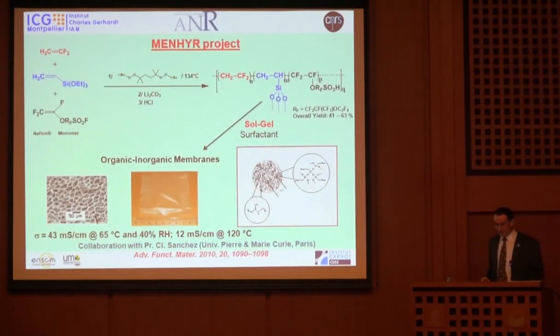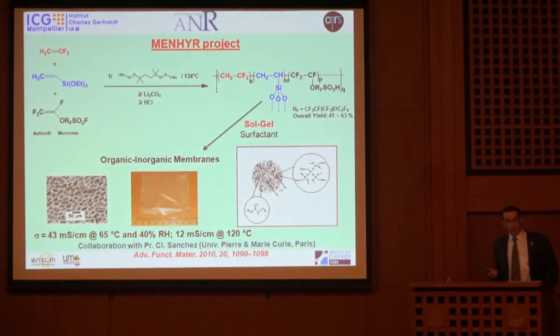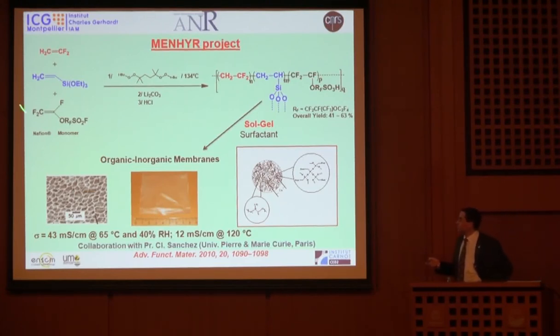So the approach we had in the lab was to come back also to the upstream. I told you that we did some copolymerization of VDF with vinyl triethoxysilane, and also this vinyl ether containing sulfonyl fluoride. Obviously, we did a bunch of different polymerizations in order to vary the content of VDF, the content of triethoxysilane, and the content of sulfonyl fluoride or sulfonic acid, in order, of course, to have some conductivity.